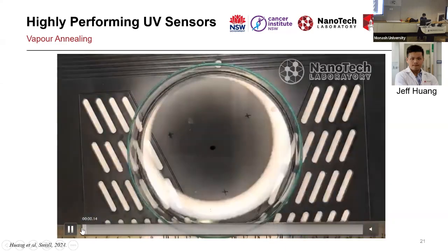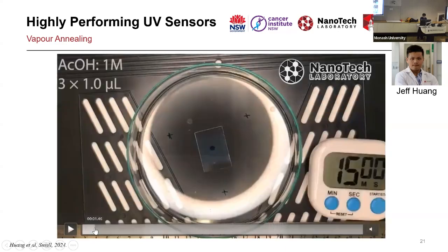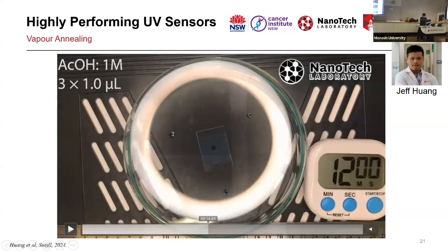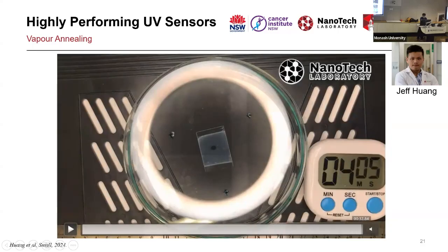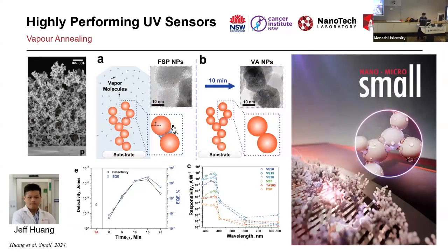So I'm just going to quickly, so this is where we started. And then this is where we ended, which again, the same scenario. I'm not going to show you the SEM images, but we actually saw that the particles merge into each other and the film kind of shrink a little bit from 7.5 micrometer to somewhere around 4 micrometer. And of course, again, it was selected for the cover photo of the